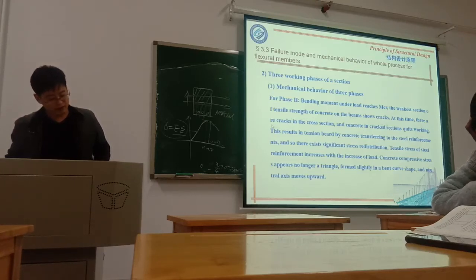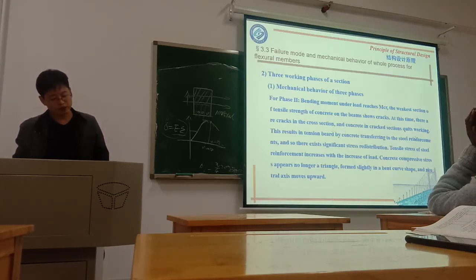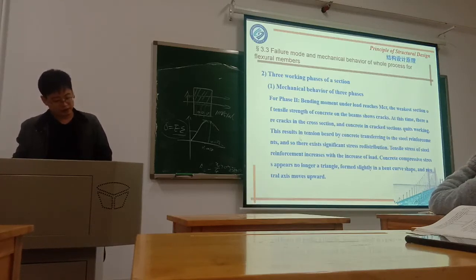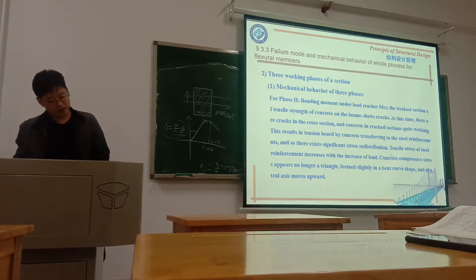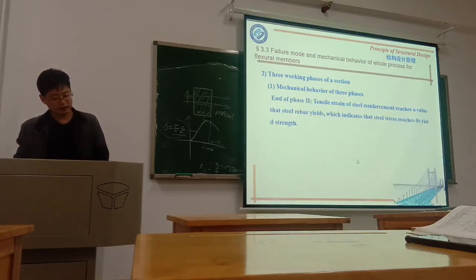At this time, there's a crack in the cross section, and the concrete in the cracked section quits work. This results in the tensile force borne by the concrete being transferred to the steel reinforcement, so there is a significant stress redistribution. And the tensile stress of the steel reinforcement increases with the increase of the load. Concrete compression stress appears no longer triangle and forms a slightly bent curve shape. And the neutral axis moves upward, as we have just introduced.